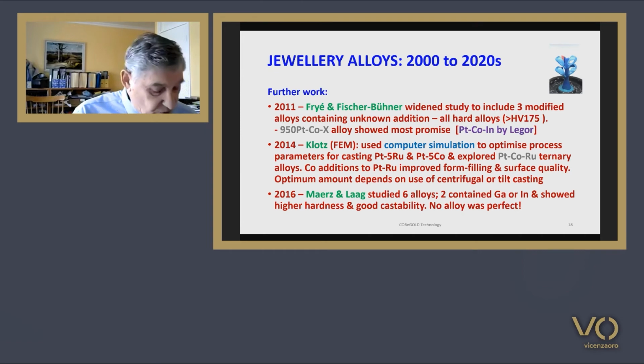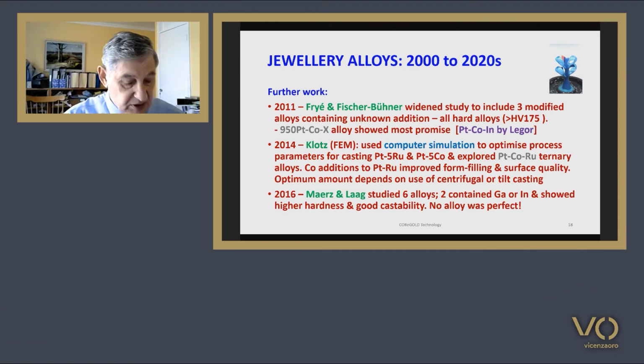In 2014, Klotz and his co-workers at FEM in Germany utilized computer simulation of casting and thermodynamic calculations to optimize the process parameters of casting 5% ruthenium and 5% cobalt alloys, and was significant in that ternary alloys of the 950 platinum cobalt ruthenium alloys were explored. They showed that improved form filling and surface quality resulted from additions of cobalt to platinum ruthenium alloys, the optimum amount depending on the casting technique used, centrifugal or tilt casting.